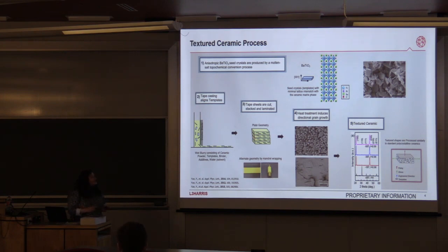And then once we do this, we go through typical heat treatments like Angie talked about earlier. Your first step is going to be to heat it up in a bisque cycle and heat out your binders and any water that's in there. Then your second step is going to be this sintering phase, which is your high temperature sintering. What I've shown here is a sample that hasn't been sintered very long. It's one where we've taken it, broken it in half, and put it in the SEM. And this is a sample that's been sintered to completion. What you can see here is your seeds, they're aligned, and growing around them is your ceramic material, and it's growing in the same domain structure as your seeded crystals.